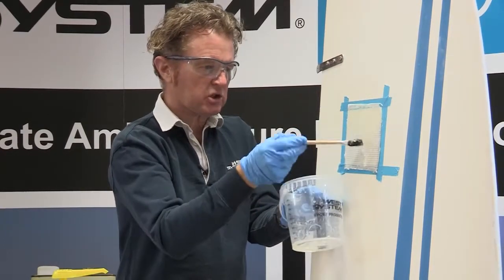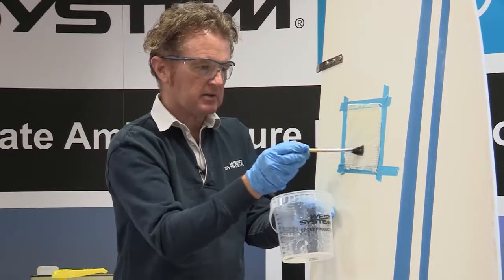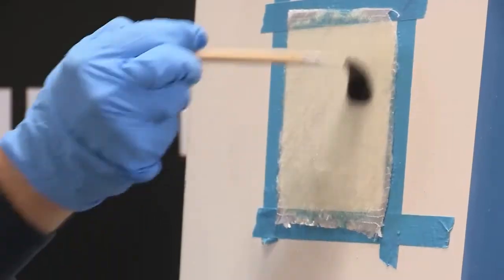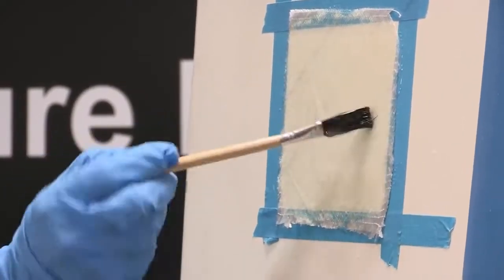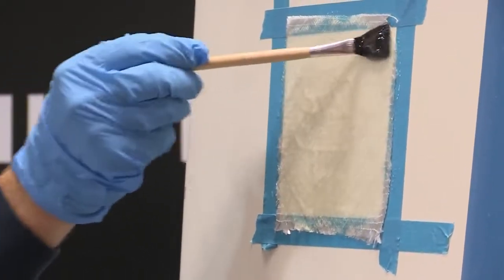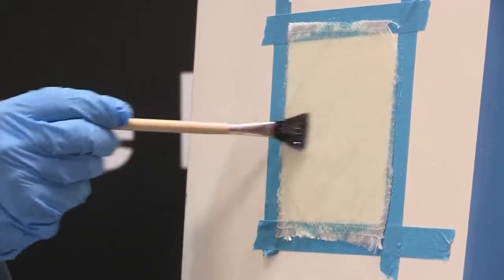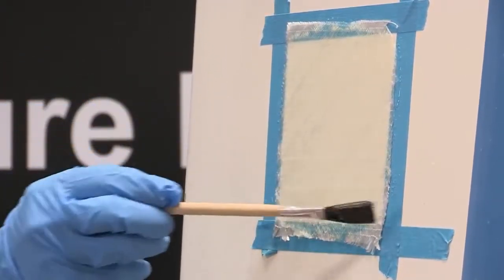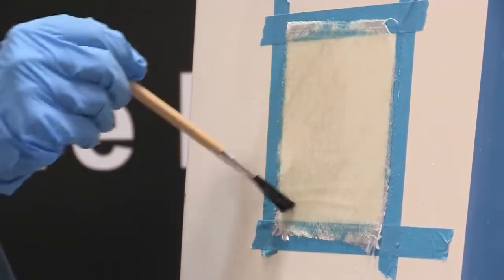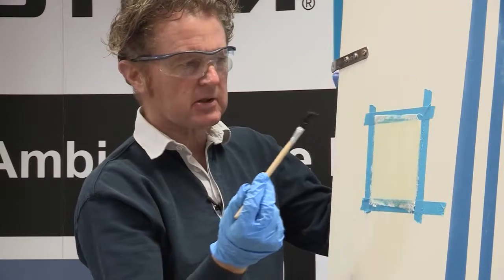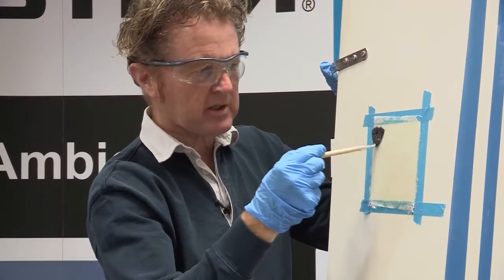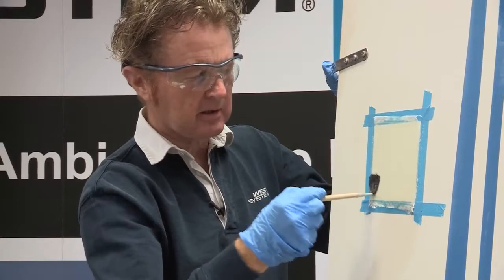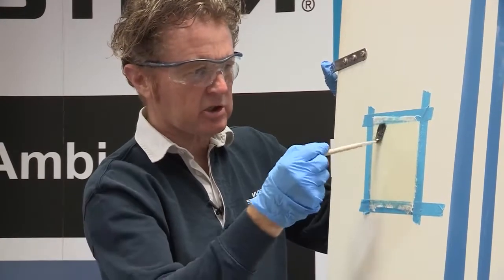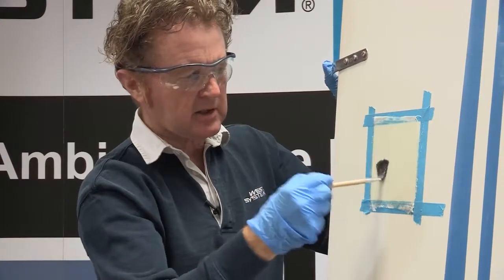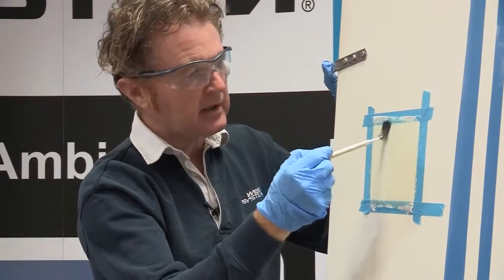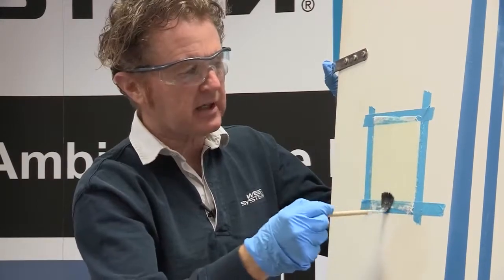And I'm simply making sure that the surface is wet out. I'm just making sure that I've wet the glass out and it's becoming transparent. That's a good indication that you've got it wet out. See, that's on there. Now I'm going to consolidate this using this brush and I'm going to stipple the glass in place. And I'm just going to work that down like this, again using the brush width as a guide. And this will compact the glass and also break any air bubbles that are present in the laminate.